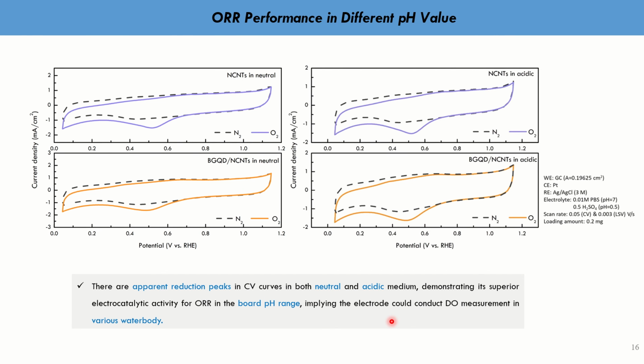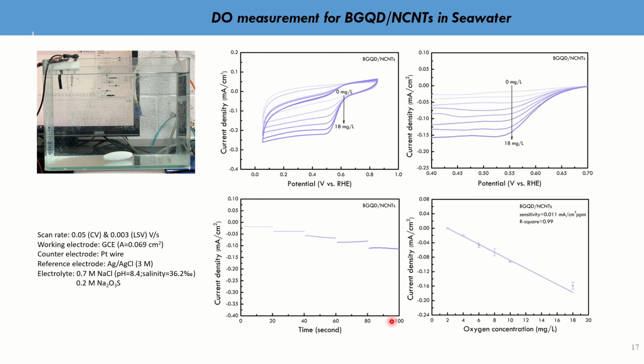Dissolved oxygen detection is not always in alkaline medium. Therefore, we also measured the cyclic voltammetry in neutral and acid medium. Results show that BGQD/NCNT can trigger the oxygen reduction reaction in neutral and acid medium, indicating that this electrocatalyst can be applied in the whole pH range. We also measured the dissolved oxygen of seawater. The result indicates that the electrocatalyst can measure the dissolved oxygen difference with a high sensitivity of 0.011 mA per centimeter squared per ppm with a high R-squared value of 0.99.